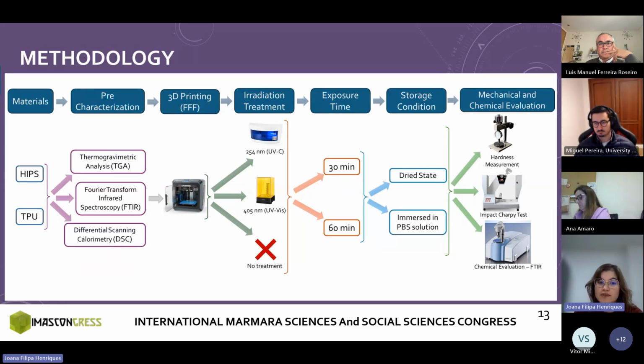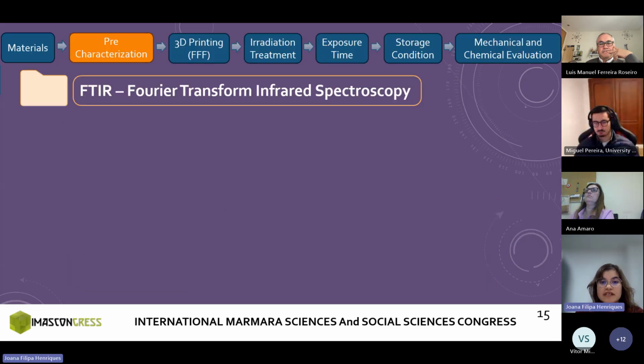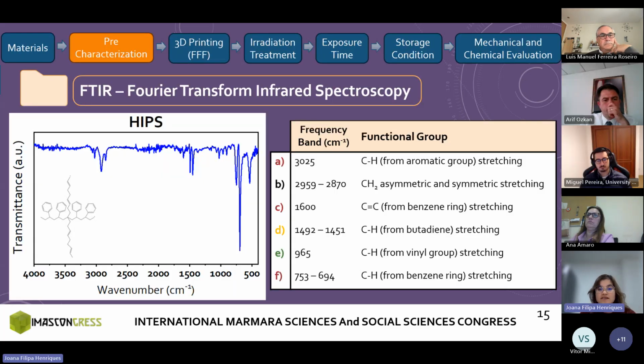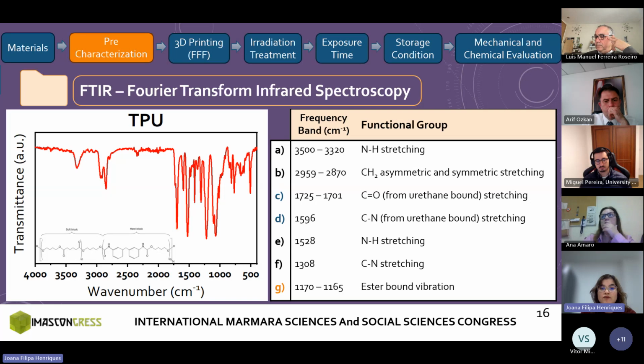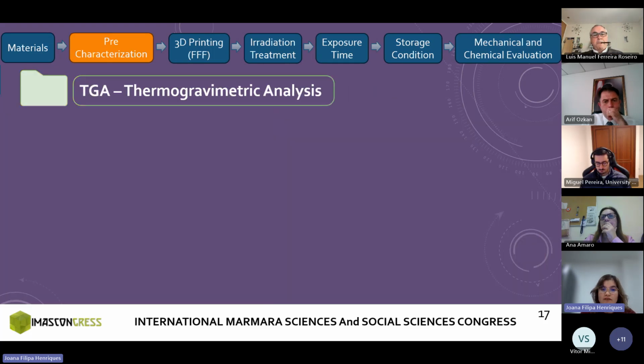and FTIR spectroscopy was used to search for significant chemical modifications. Firstly, the filaments were chemically characterized to identify the functional groups of each polymer, and while the spectrum of HIPS presents the characteristic bands of aromatic groups and butadiene, the spectrum of TPU shows the presence of urethane and ester bonds, which are characteristic of this polymer. Therefore, it can be assumed that the eventual presence of additives during the process of formation of these filaments did not induce significant changes in the chemical composition of the filaments.